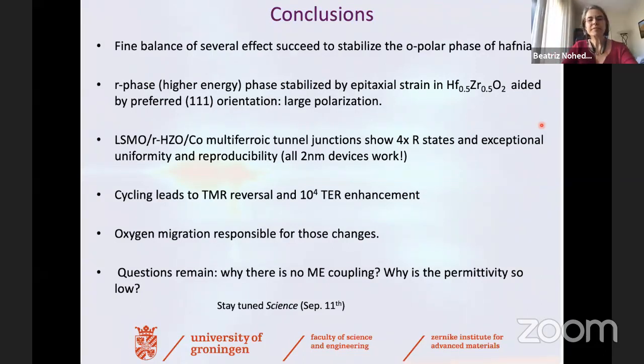Yeah, so there is. We can look at these materials now with electron microscopy. We can see that these materials are indeed polar. So that is the microscopic understanding. You need a polar material, a material without inversion center. Now, in order for the material to be ferroelectric, you still need that this material can be switched by electric field, and that's not happening in all polar materials. But indeed, the first thing you need to look for is a polar material, a material with a polar space group, so a crystal structure that doesn't have inversion center.